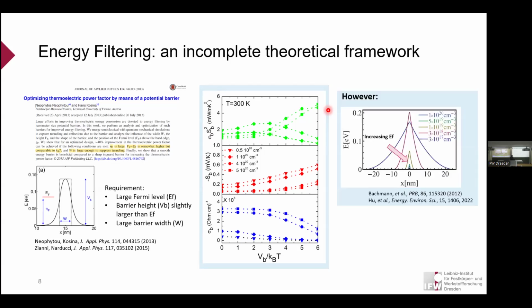For example, when the material has a high Fermi level, it usually means the charge carrier interaction is strong, and whatever boundary you have, at the grain boundary or whatever boundaries, they'll be effectively screened. So that means the charge carriers will not see these barriers when the number of them is too much. So that means you cannot effectively induce this effect.